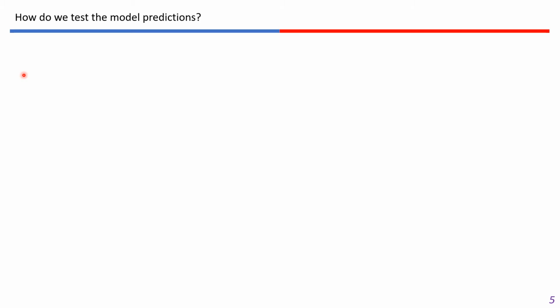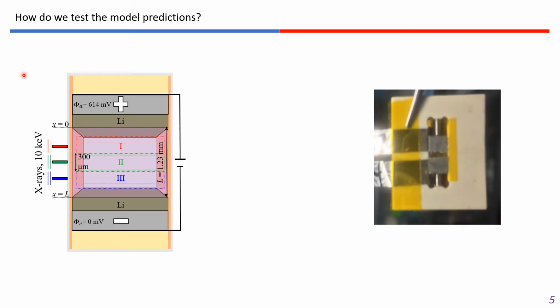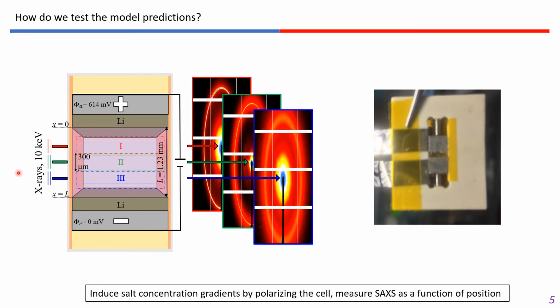In order to test these model predictions, I've developed a cell to use small angle X-ray scattering to study the morphology of the block copolymer electrolyte during DC polarization. The cell is shown schematically on the left and a picture of the cell is on the right. We simplify the cell by using 2 lithium electrodes, across which we can apply a potential to pass DC current, and then we raster the X-ray beam across 3 different positions to measure the small angle X-ray scattering patterns shown here, to study the morphology of the electrolyte as a function of position during polarization.